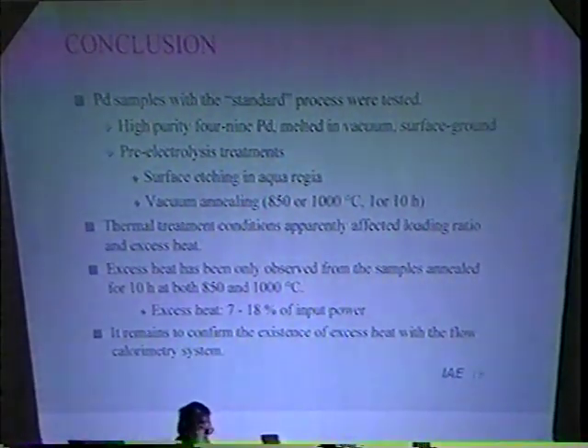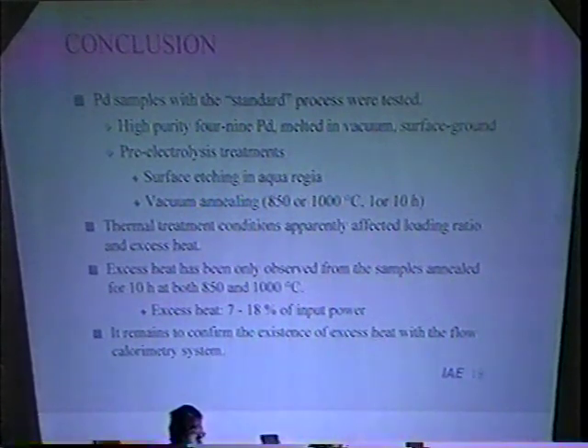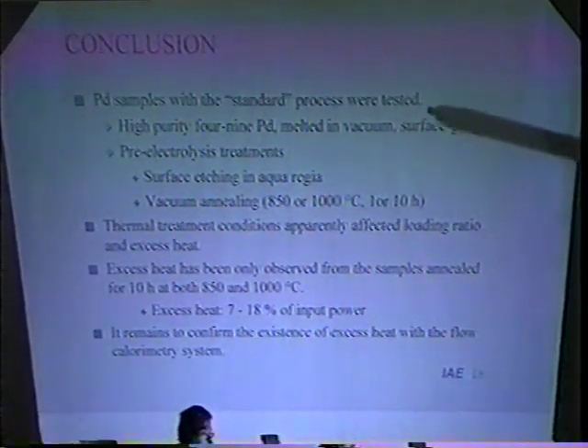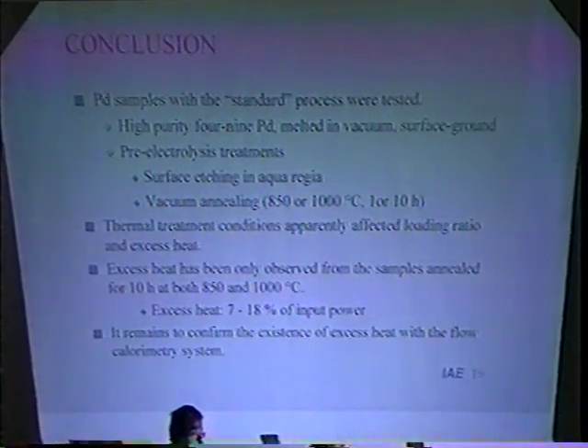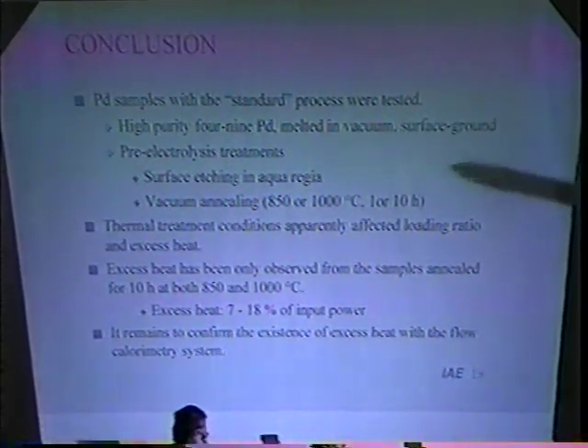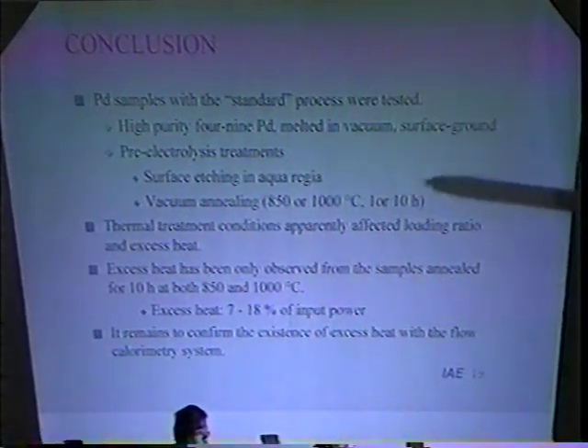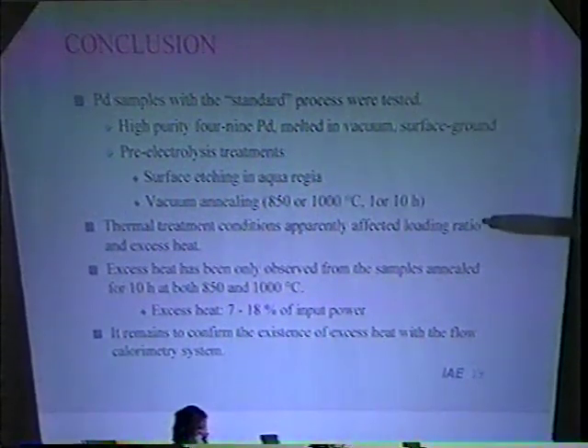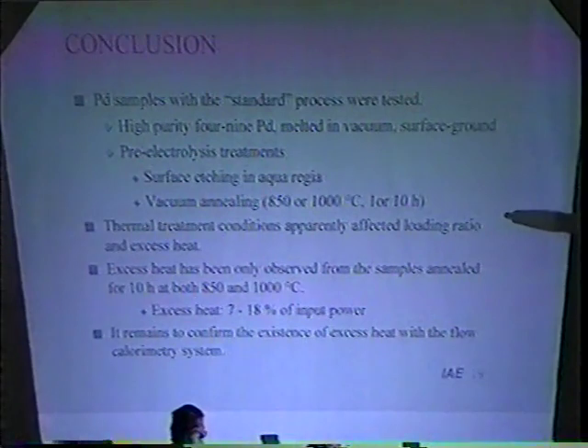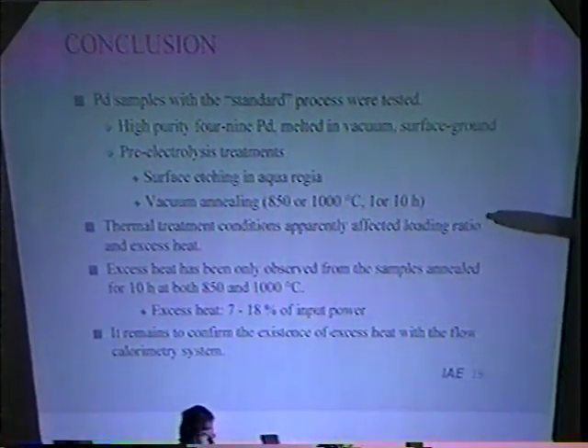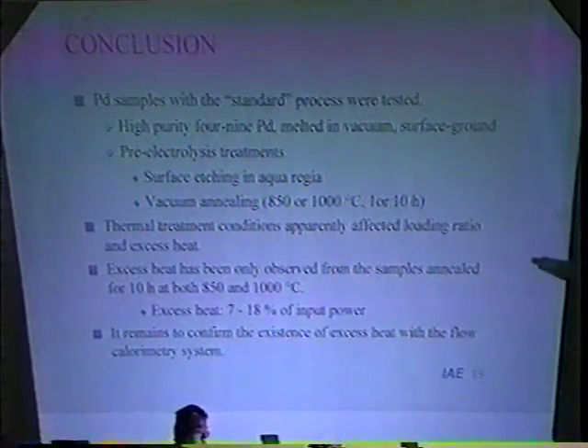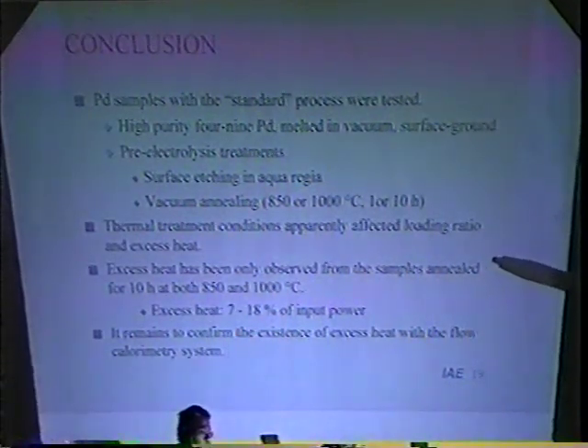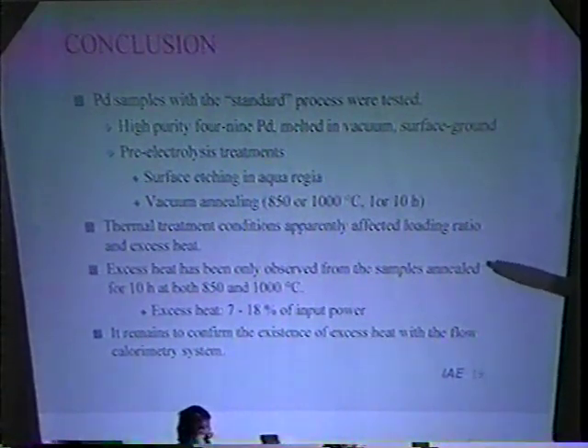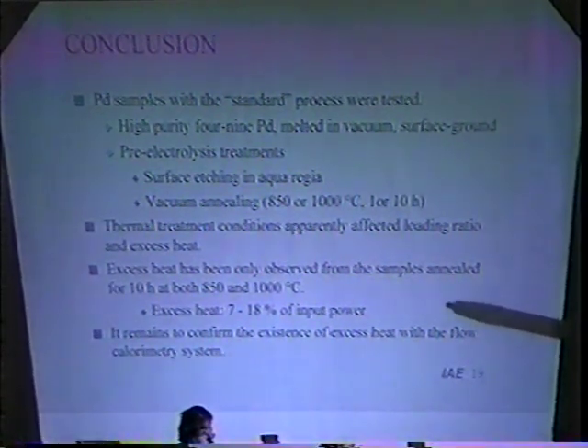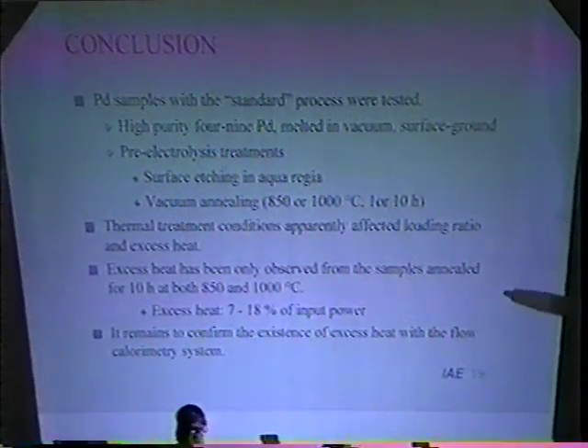Conclusion. Palladium samples with the standard process were tested. The samples were high purity four-nine palladium, melted in vacuum, surface ground, and treated by surface etching in aqua regia and vacuum annealing. The thermal conditions apparently affected loading ratio and excess heat. Excess heat has been only observed from the samples annealed for 10 hours at both 850 and 1000 centigrade. Excess heat was 7 to 18% of electric input power.